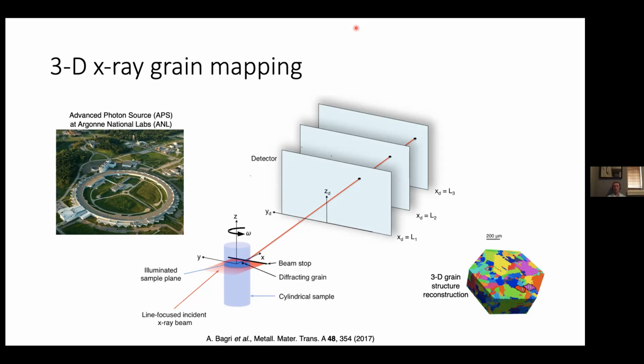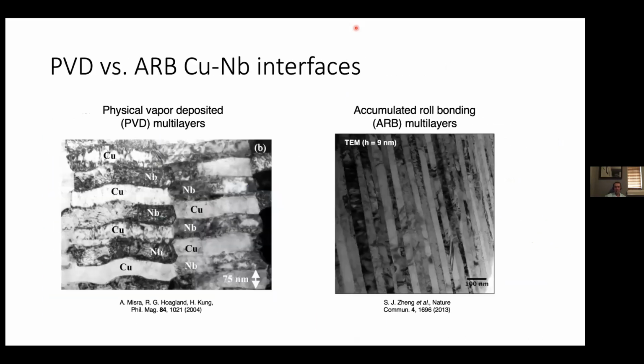So let's say that you have a grain boundary or an interface that comes out onto a free surface. If you know the surface energies of the facets that are coming out on the surface, then you can look at the angles of the surface with respect to the grain boundary that forms at the groove on the surface. There's a little groove that forms at the surface. And if you look at those contact angles, you can figure out the relative energy of the boundary relative to the energy of the surface. So that's typically how people have done it, and actually I might be able to give you an illustration of that here.